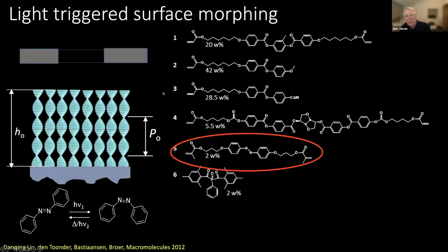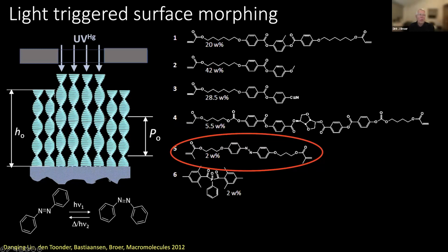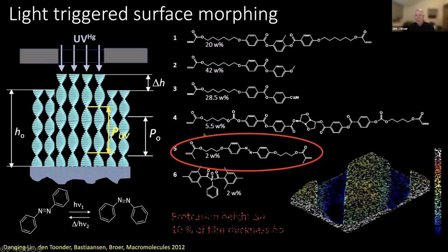So if you now make a composition where we have present at least the chiral component, which is responsible for the helices, and we have now an azobenzene with response to light, the azobenzene converts from this trans state to the cis state, and by doing this, it affects the order of the neighboring molecules, so we are reducing the total orientation in the liquid crystal film that you have made here. So now if you are exposing this with light, then what you might expect is that due to the reduction in order at the exposed area, you will have an increase in volume, the system expands, and you will form a small protrusion in this case.